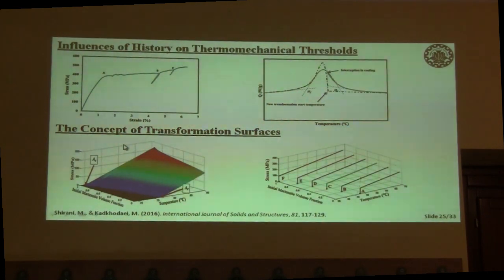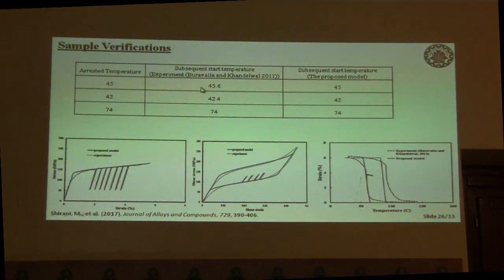We introduced the concept of a transformation surface instead of a transformation phase diagram, a three-dimensional surface in which the initial value of martensite volume fraction plays a role. Compared to experimental results, if I arrest the temperature, meaning I induce incomplete transformation, at 45 degrees for example, the subsequent start temperature is 45.6 experimentally, and our prediction is 45. If I interrupt the transformation at 42, experimental observation is 42.4, and our prediction is 42. If I interrupt the transformation at this temperature, all the results are the same. This way I can predict the so-called strain hardening.